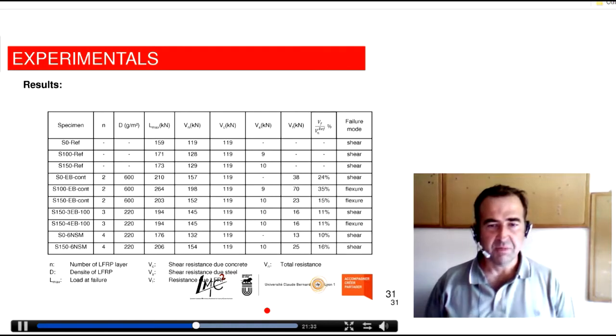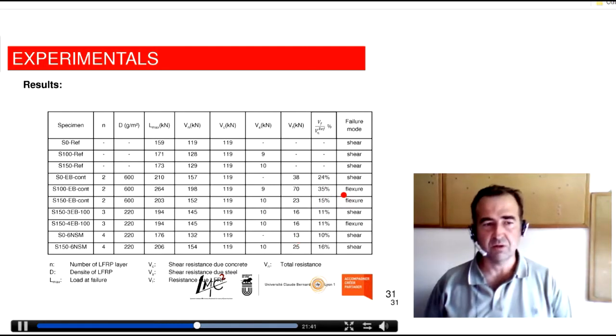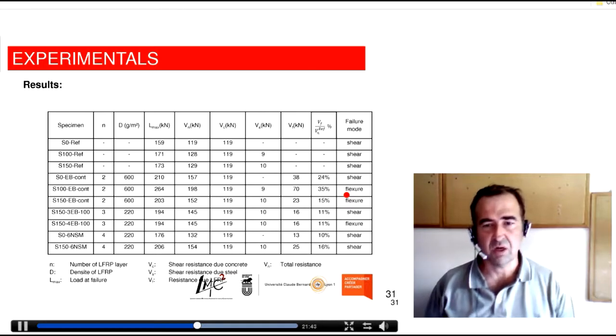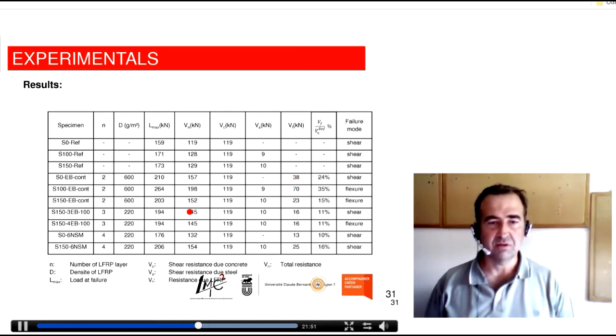So all the results may be summed up in this slide. You observe here that when the level of strengthening was too high, we didn't get the shear failure and we get the flexural one. But in most of the cases, we obtain the shear failure as expected.